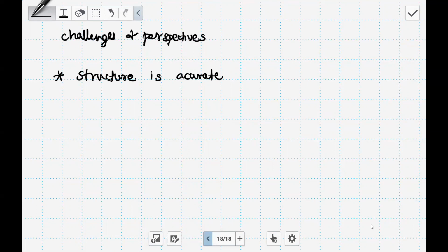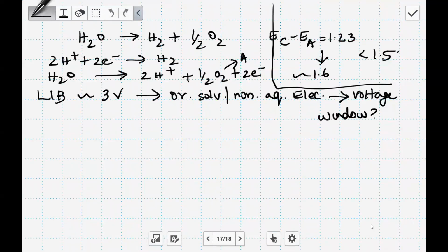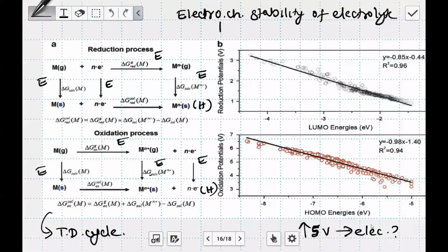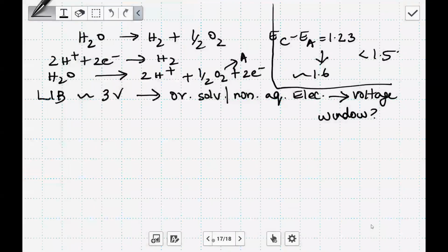Okay, so just one last point I want to emphasize is electrolyte stability. In fact, this is very important for this phenomenon called solid electrolyte interphase, right? So this is a very complex structure. It's not very clear what is the structure of the solid electrolyte interphase. The SEI formation: the anode SEI is more important than the cathode SEI, but both SEIs exist. That actually gives stability to your electrode. There's no continuous dissolution of the electrodes. And this SEI is formed by the decomposition of the electrolyte in the first few cycles, right? So that is known.